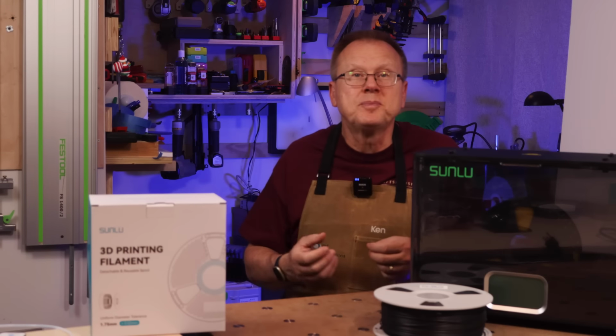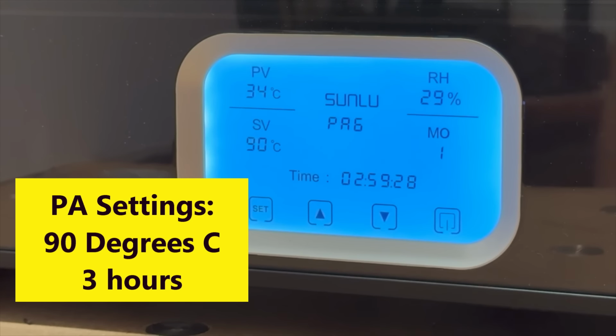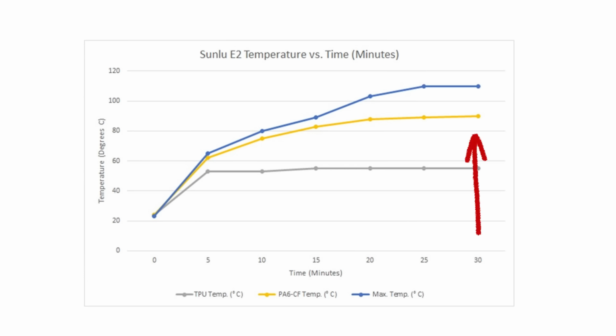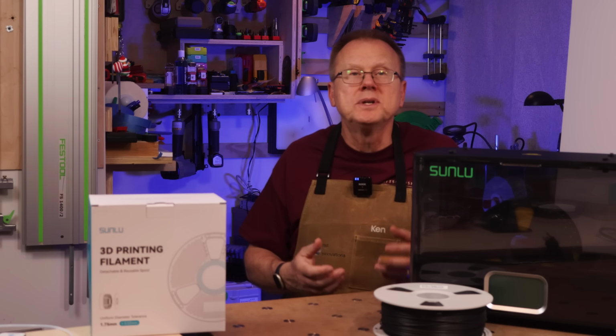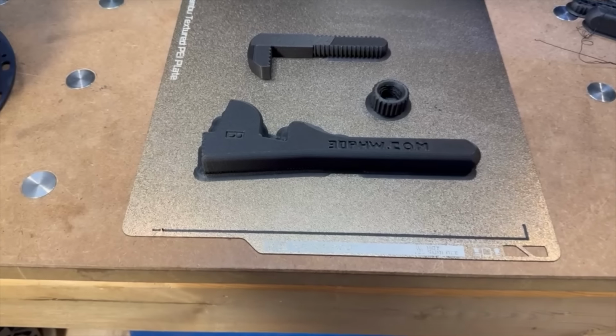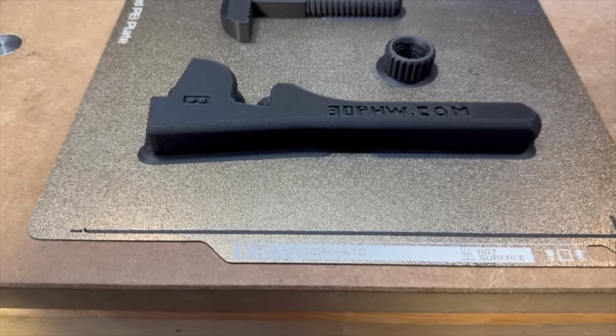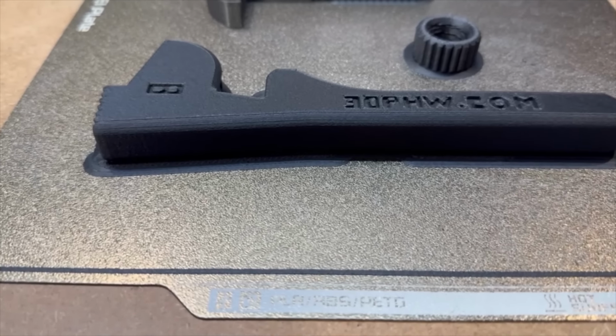Then I placed the PA6CF into the E2 and I picked the PA preset setting of 90 degrees C for 3 hours. The E2 took 30 minutes to reach the 90 degrees set point. After drying, I printed the same pipe wrench and I was amazed at the results. It was the most defect-free pipe wrench that I've ever printed.